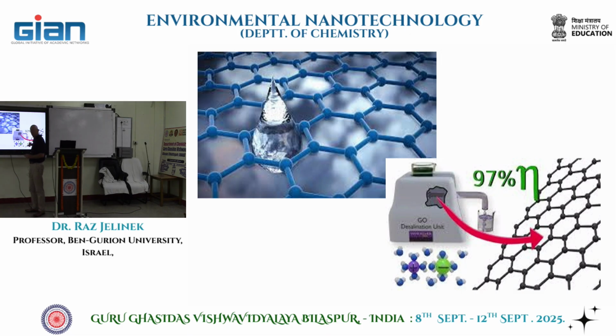When they get closer to the graphene sheet, and graphene has all these electrons, you can get the electrons and reduce the positive ion or oxidize the negative ions. And then what happens is that these ions, because of the reduction or the oxidation, become metallic and they aggregate and they sit on the graphene and they don't go through. So that's why graphene is such a good membrane, such a good filter.